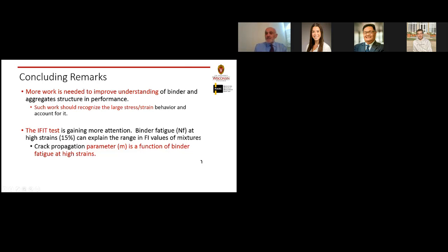Finally, I would like to really give a comment on the IFIT. I think this test is gaining more attention. I think the test is not at all useless, but actually we can now explain why the M value, the post peak slope, is different from one mix to the other. We can very clearly show people why aging, that we know very well reduces the M value, is a real phenomenon that needs to be considered and included into any mixture specification.